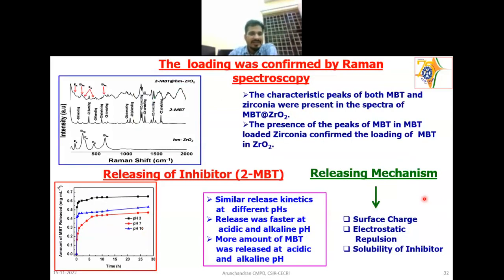And then one has to confirm the loading of the inhibitors. So we got the signature for the MBT on the hollow mesoporous zirconia. So this confirmed that the inhibitor got loaded there. And then we need to find out the release. Of course, we loaded that one, but is it able to release or not?